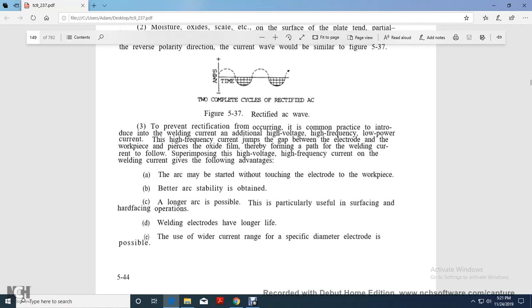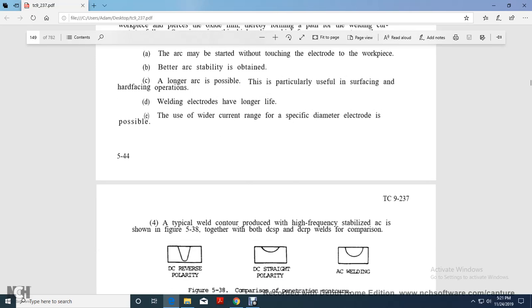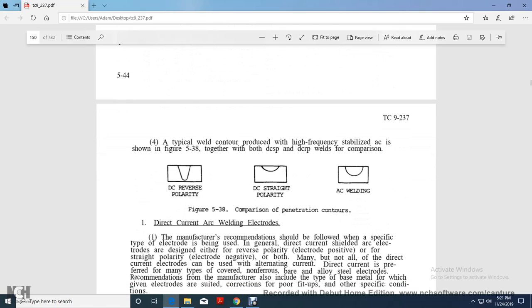Superimposing a high voltage, high frequency current on the welding current gives the following advantages. The arc may be started without touching the electrode to the workpiece. Better arc stability is attained. A longer arc is possible, which is particularly useful in surfacing and hard-facing operations. Welding electrodes have longer life. The use of a wider current range for specific diameter electrodes is possible. A typical weld contour produced with a high frequency stabilized AC is shown in Figure 538, together with both direct current straight polarity and reverse polarity for comparison.